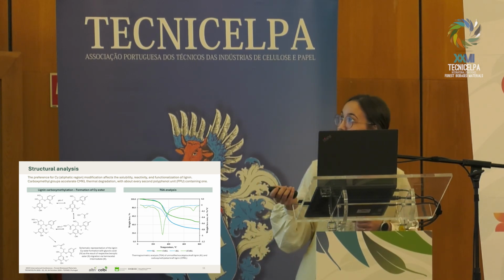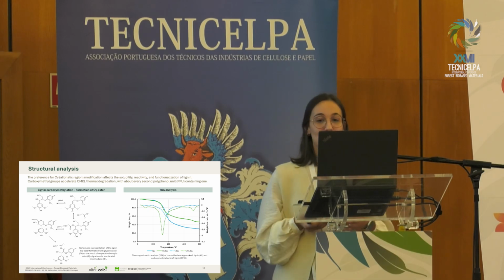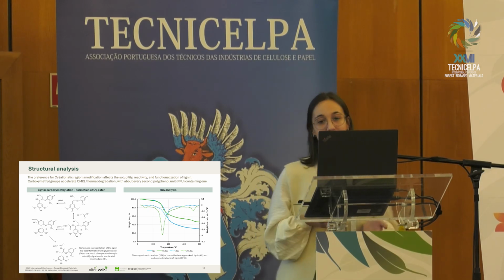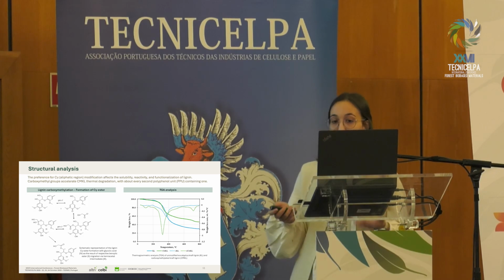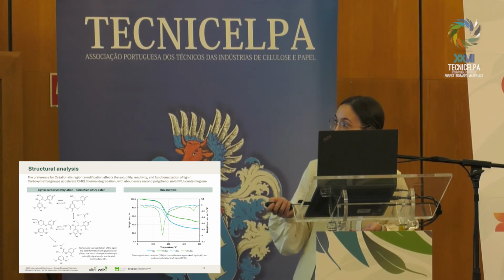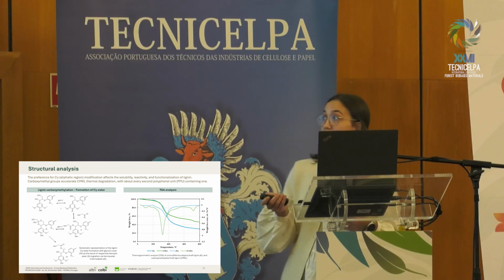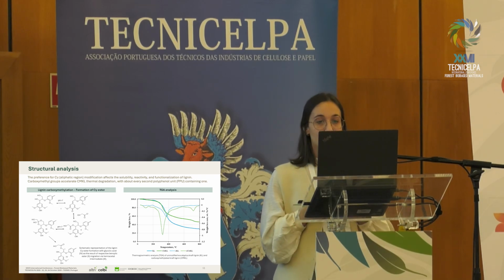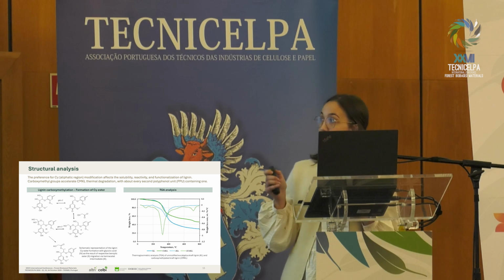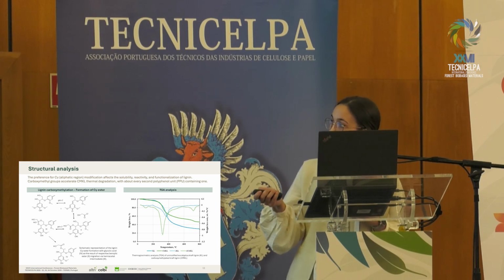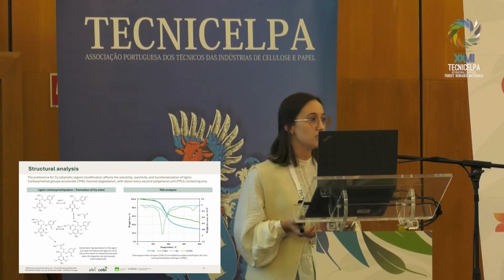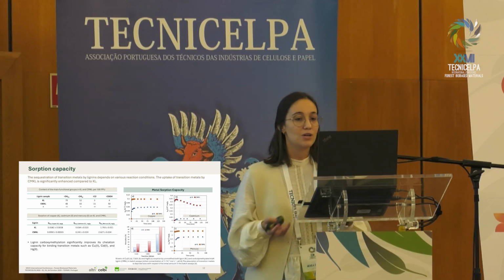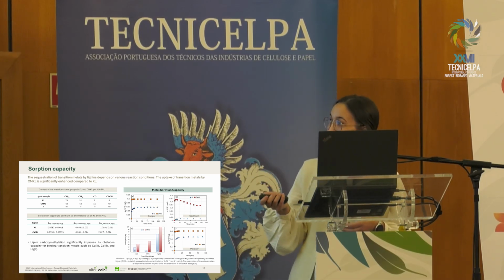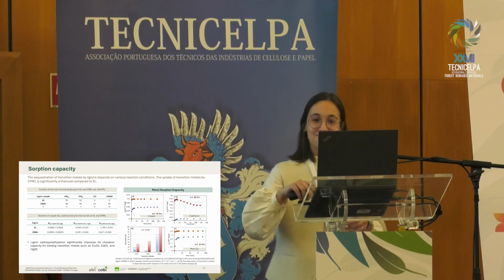They appear within the spectral range in here that belongs to the methylene carbons in carboxyl moieties and the esterified methylol in both syringyl and guaiacyl units. But this analysis also showed that some esters form at the methylol position, at the gamma carbon, and some ethers form at the benzylic position at the alpha carbon. And those structures had not yet been described in the literature. So the aliphatic hydroxyl groups do react.